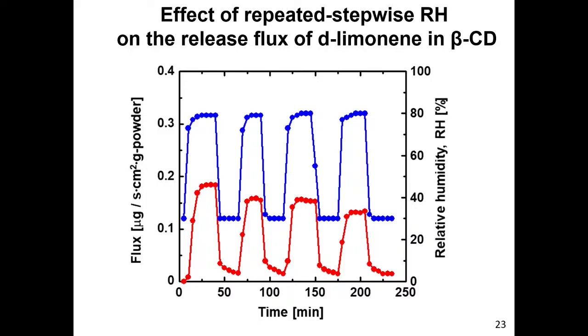So when we change the humidity, we can see this kind of stepwise change. High humidity condition, we can see the release of the flavor compound. But low humidity condition, we cannot see the release. So when we control the environmental temperature and humidity, we can control the release rate of the flavor in cyclodextrin.